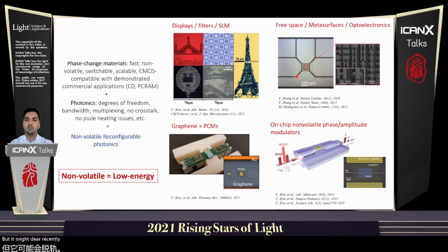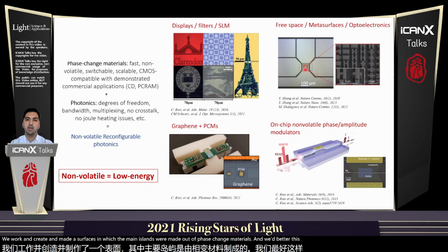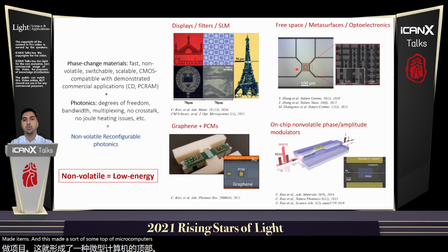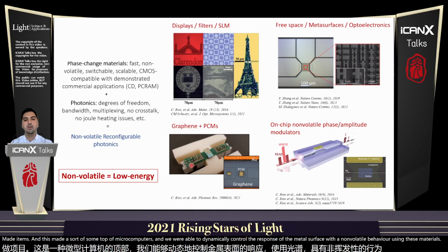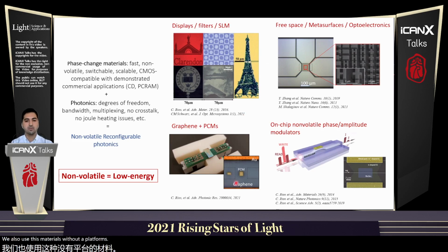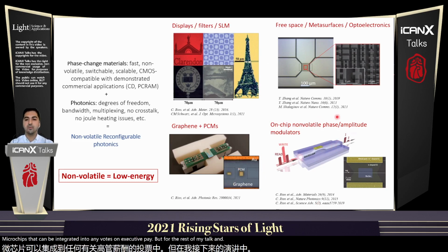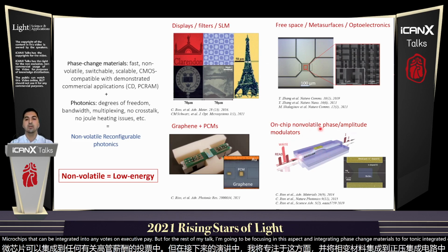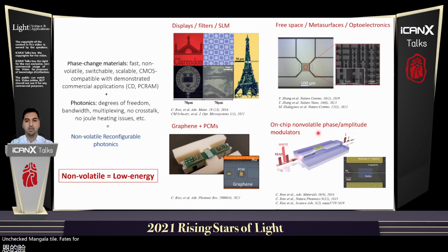At MIT recently, in my years as a postdoc, we worked on creating metasurfaces in which the meta-atoms were made out of phase change materials, and we embedded these meta-atoms on the metasurface on top of micro heaters, and we were able to dynamically control the response of the metasurface with a non-volatile behavior using these materials. We've also used these materials with other platforms such as graphene, looking for a transparent micro heater for applications such as transmissive metasurfaces or micro heaters that can be integrated to any photonic circuit. But for the rest of my talk, I'm going to be focusing on integrating phase change materials into photonic integrated circuits and finding on-chip non-volatile phase or amplitude modulators.